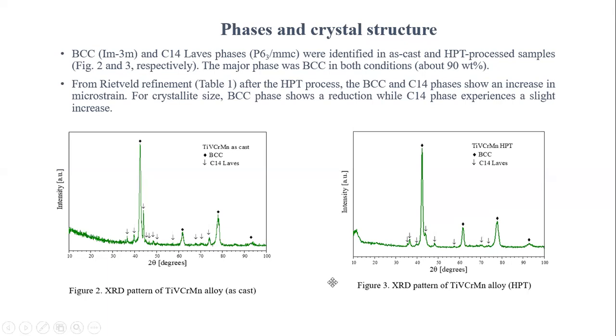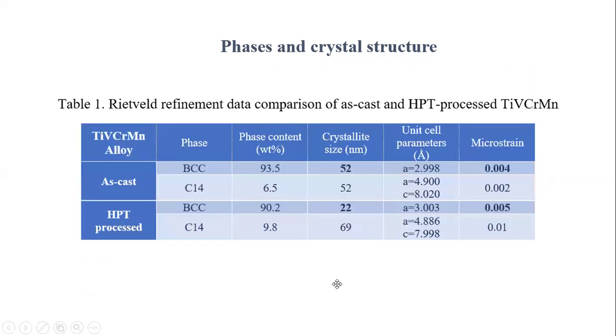XRD results show that BCC and C14 Laves phases were identified in as-cast and HPT processed samples. The major phase was BCC in both conditions, about 90 wt%. From Rietveld refinement, after the HPT process, the BCC and C14 phases showed an increase in microstrain. For crystallite size, the BCC phase shows a reduction while the C14 phase experiences a slight increase.